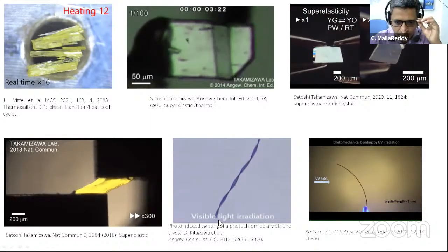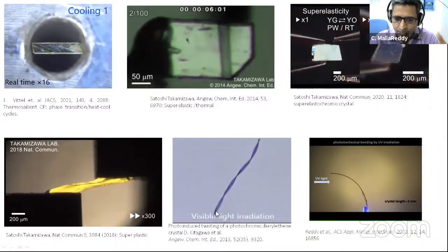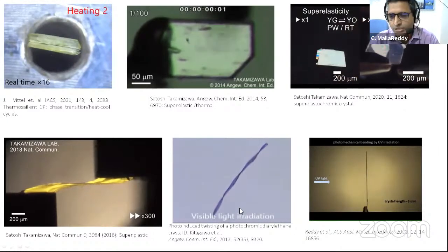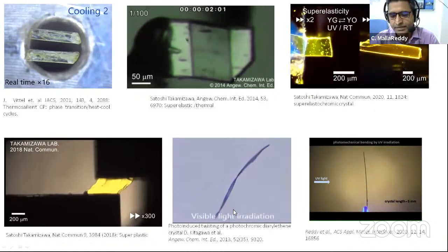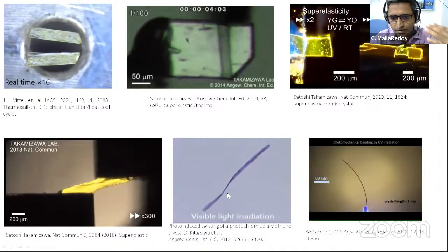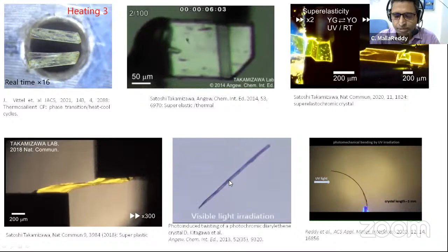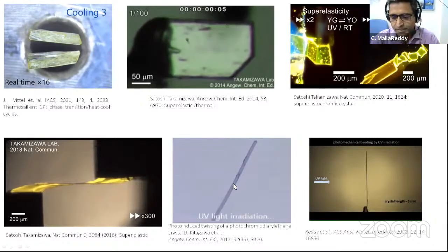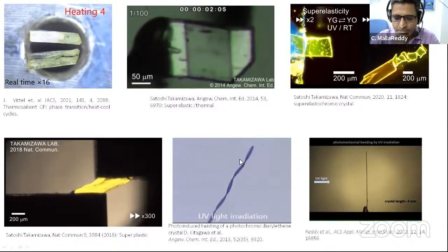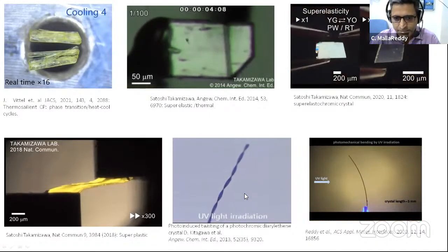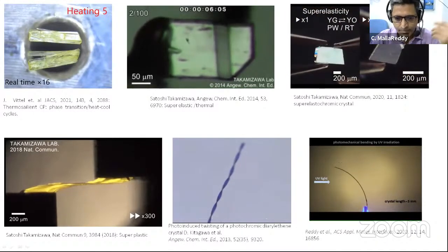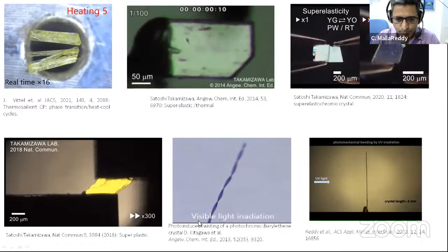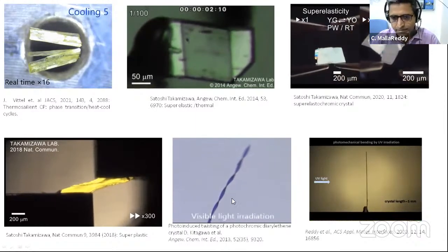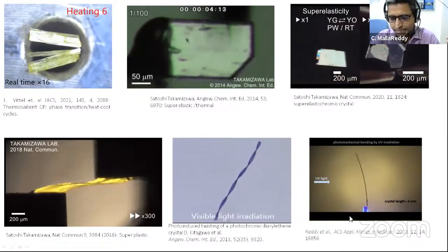And here it is a photochemical reaction, and if you put these crystals under light, they start twisting. Again, once the reaction starts, it is anisotropic. So that is why the extent of reaction at different locations is different. So that is why these crystals start rolling, and then you remove the light, and you put a different light, then again it comes back. So that is what basically happens here.